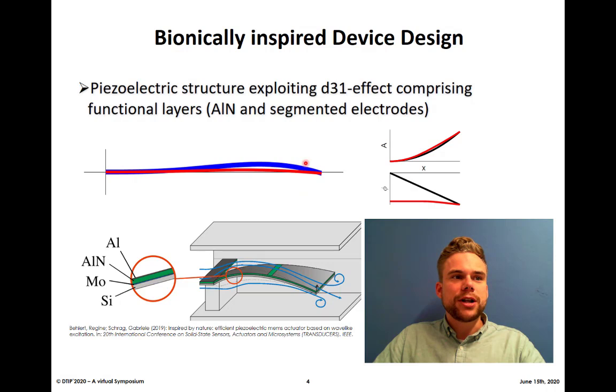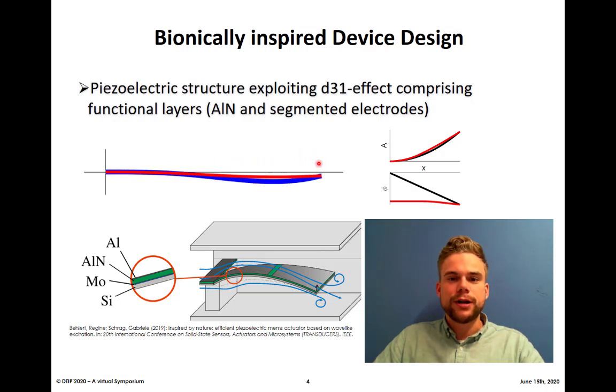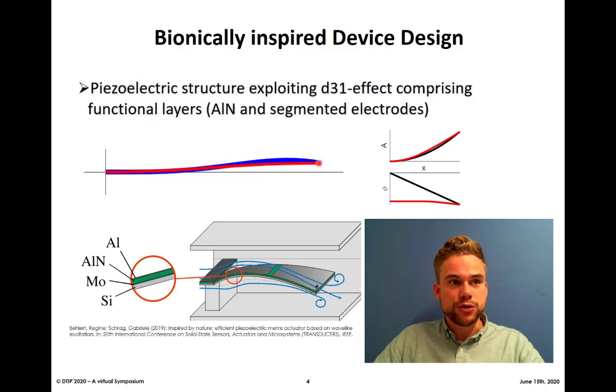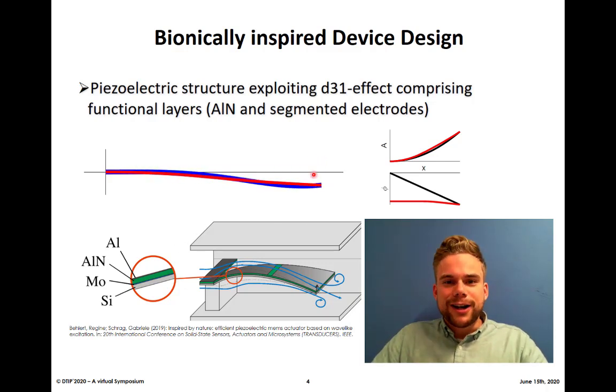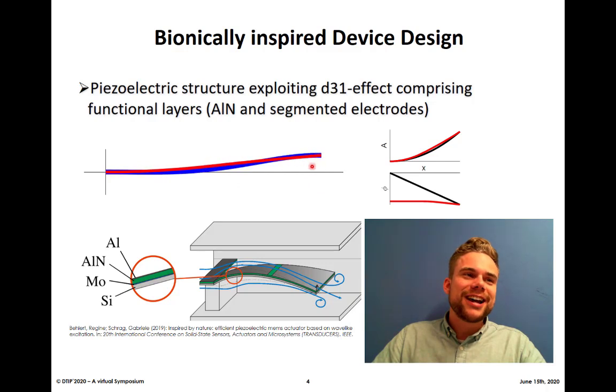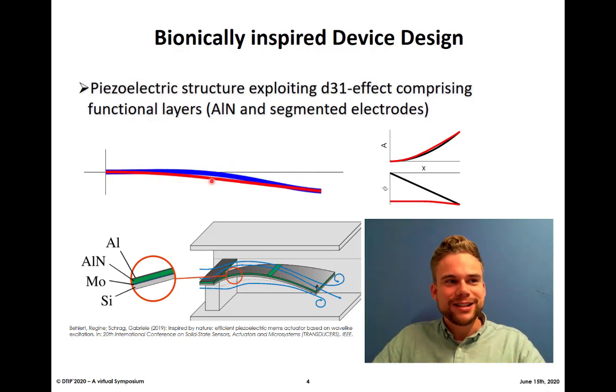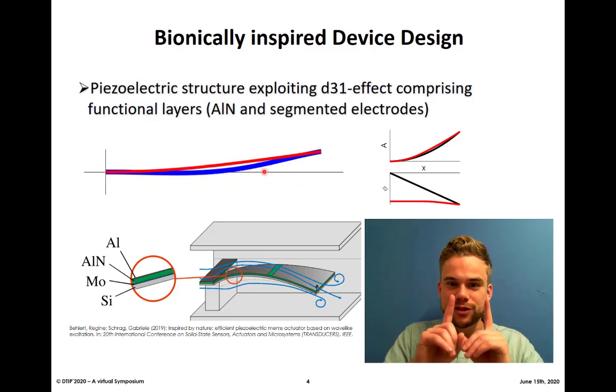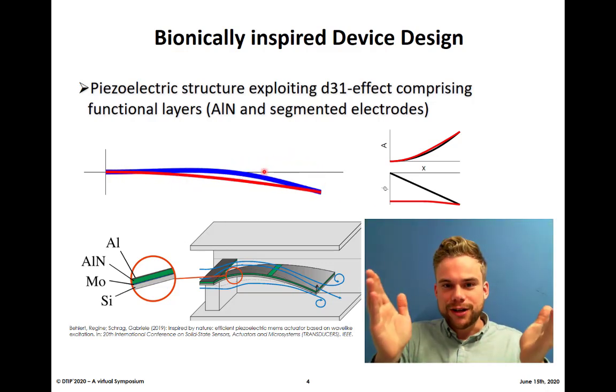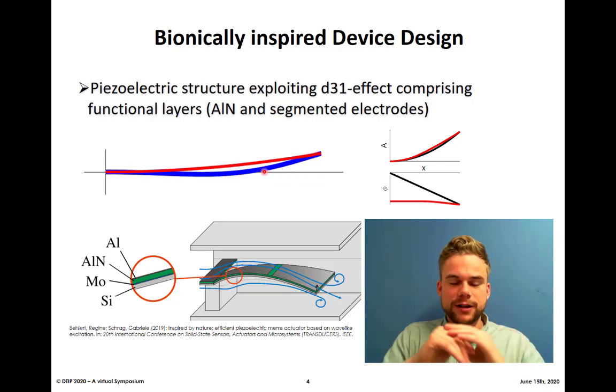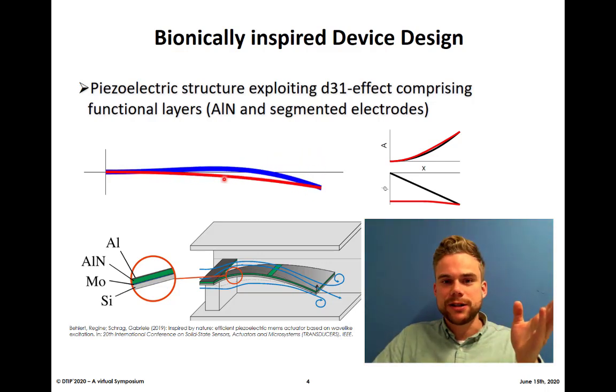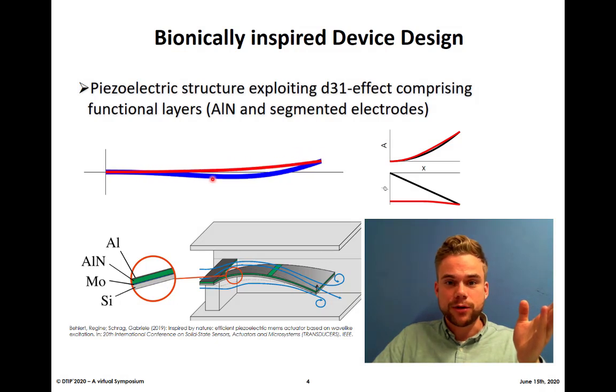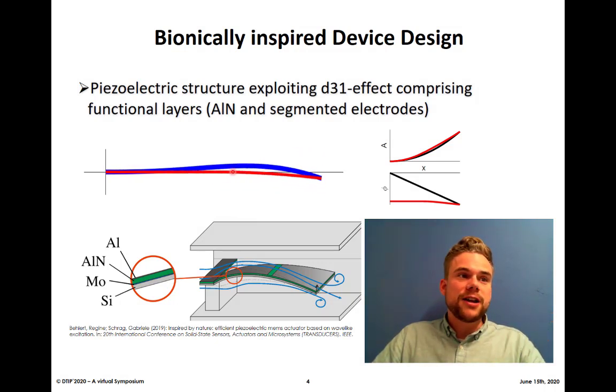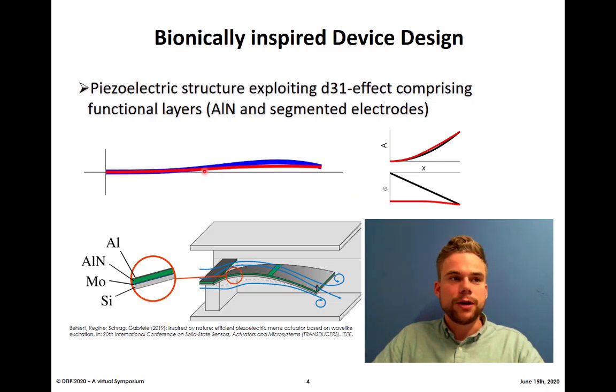So this is the theoretically possible bending line for an imitation of undulation movement with just two electrodes. Of course, I agree it's not as beautiful as the blue line, which would be the perfect undulation with a phase shift between each element. But since we just have two electrodes in this design, we can basically reach theoretically the red line's bending curve. But you still see that there is an undulation happening here because we have this phase shift when the flapper goes through the zero line here.